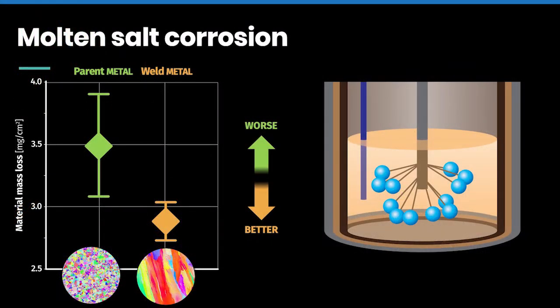After confirming that the strength of the weld metal is satisfactory, we can move to molten salt corrosion testing. Again, for this test, we extracted small specimens from the weld metal and from the parent metal, and we submerged these specimens into the molten salt at 750 degrees for 1000 hours. We measured the mass of the specimens before and after the exposure to the molten salt, and you can see the results on the right hand side. From these results, you can see that the weld metal specimens actually lost less of their mass when compared to the parent metal specimens. This simply suggests that actually the weld metal has better molten salt corrosion performance than the parent metal. This is again at the macro scale.